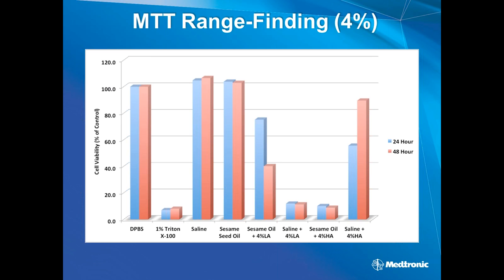And now here's sesame oil that has lactic acid in it. And you'll notice when we put lactic acid in sesame oil, it behaves differently than when you put it in saline. That's because lactic acid is very soluble in water, so it's a polar molecule, and it's not so soluble in oil, which is our nonpolar solvent. After 24 hours, with lactic acid in sesame oil, we still have pretty good cell viability, about 50%, but after 48 hours, you can see more of these cells have died. Lactic acid dissolves really well in saline, and we've got very good cell death here. Obviously, with this 4% solution, we're killing about 90% of the cells.